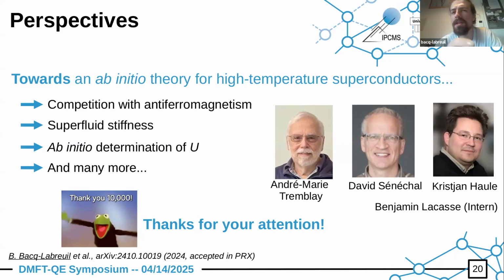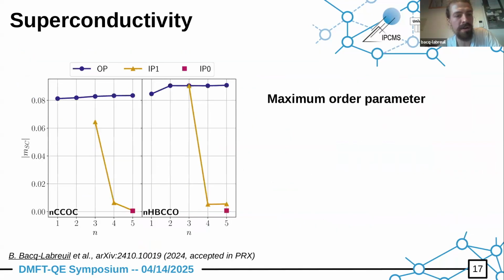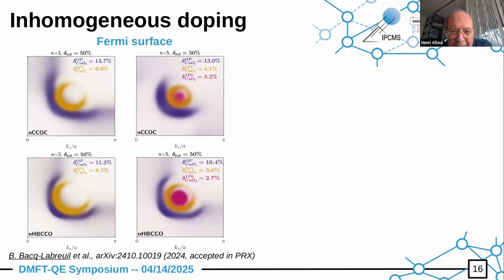So what you said is that in the outer planes, you have passed the overdoped regime, and you can be overdoped in the outer planes and underdoped in the inner planes, which is what you are telling us. So you are telling us that you have fewer charges in the inner planes than the outer planes. Yes. So it goes in this direction, which is that the layers are somewhat decoupled, and this is what was observed in NMR. This is what we see also, that the layers are quite decoupled.